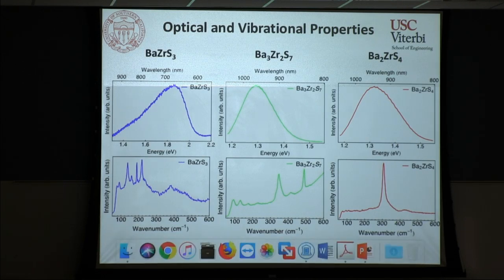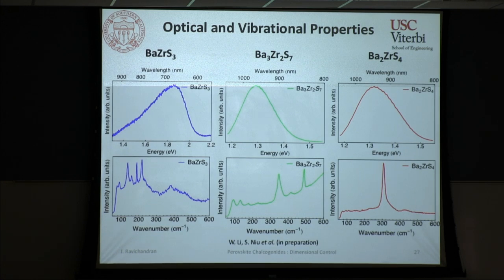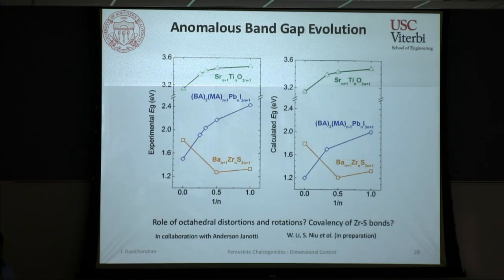Okay, so let's try to put all of these things in perspective and see how the Ruddlesden-Popper band gap evolution works for various materials. Now, I mentioned that strontium titanate is a very nice perovskite oxide. So this is the band gap evolution for strontium titanate Ruddlesden-Poppers. We have picked the case of methylammonium lead iodide, which is the other perovskite that people like, and that also shows the same increase in band gap as a function of the layer thickness of your perovskite. But in our case, the barium zirconium sulfur based Ruddlesden-Poppers show exactly the opposite trend. It basically shows a redshift.